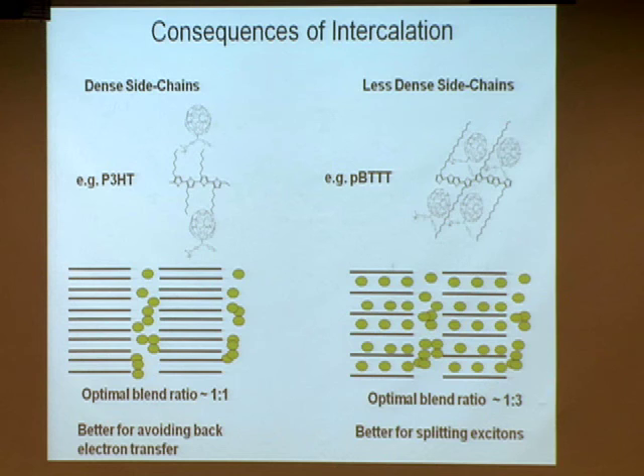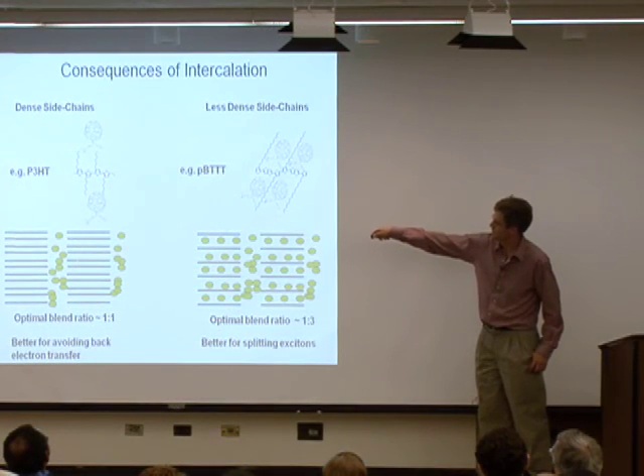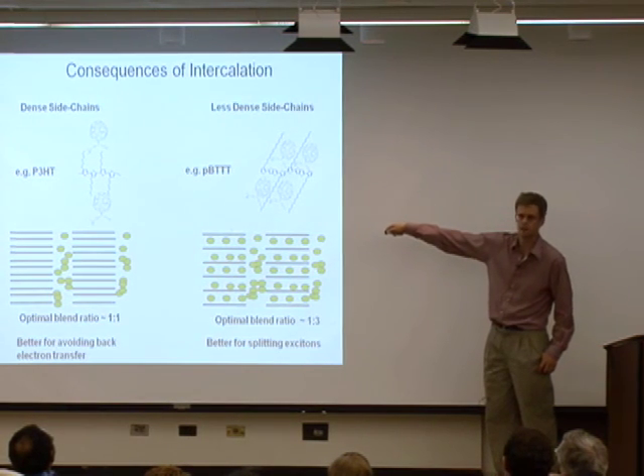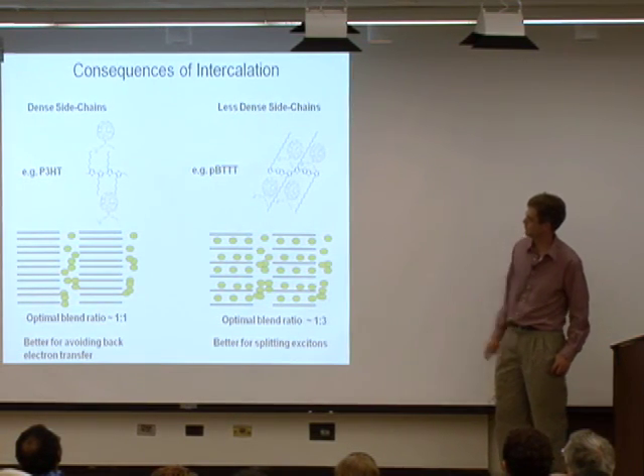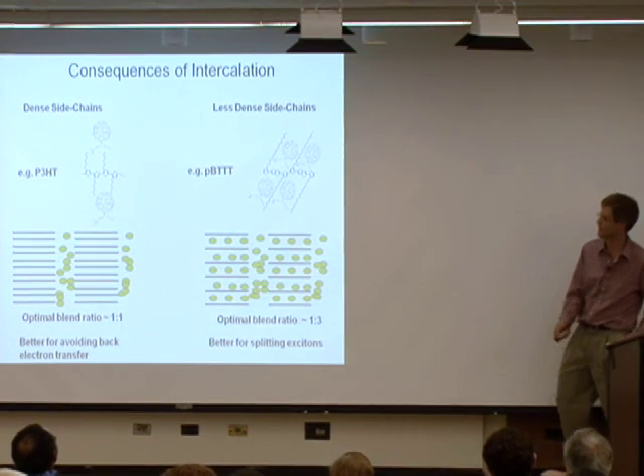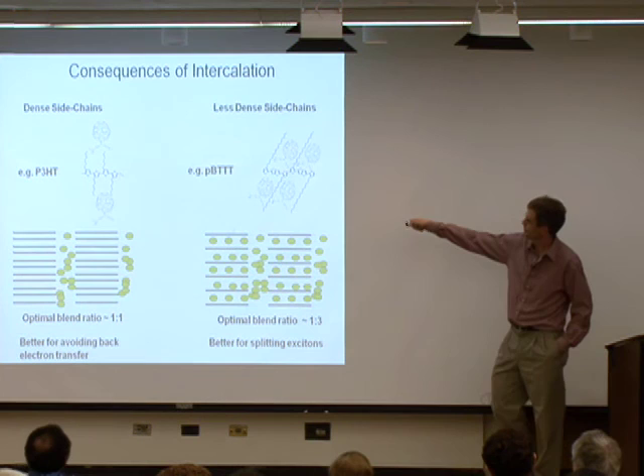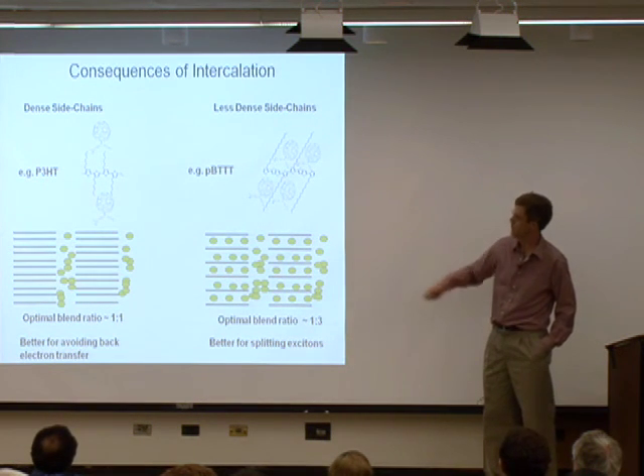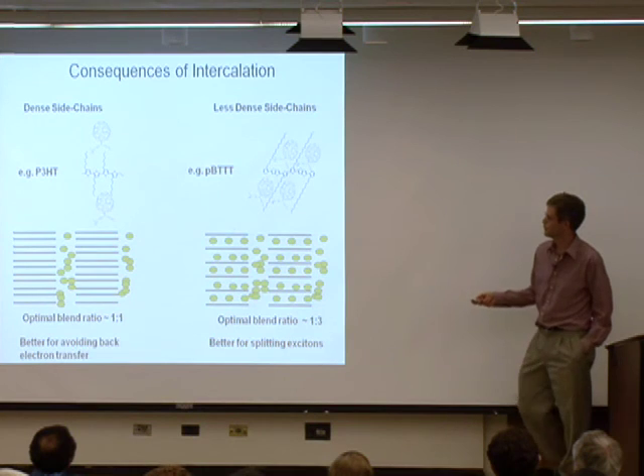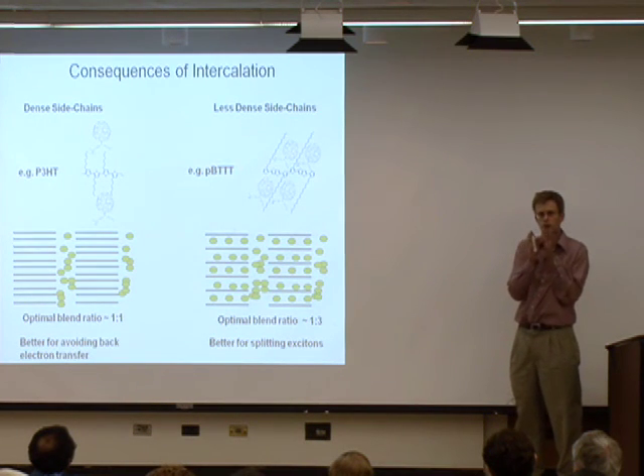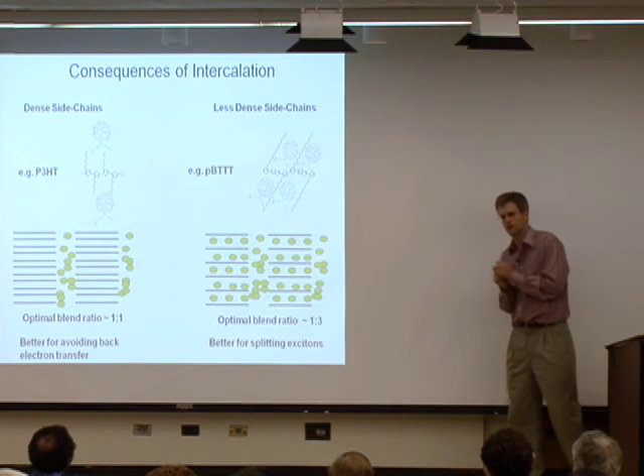So here's an example of a polymer where you don't get this intercalation, and then you have well-defined crystals of just pure polymer and pure fullerene. And we find that works really well as long as the crystals are small enough for the excitons to make it to the interface. So if they're about 10 nanometers across or smaller, we find that this works really well. The other thing we've learned is that when you don't have the mixing, it's best to have about a 1-to-1 ratio of the 2 components. You want to have an equal volume of hole transporting material and electron transporting material.